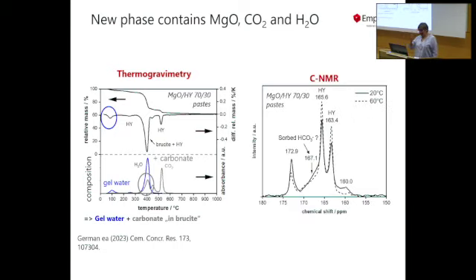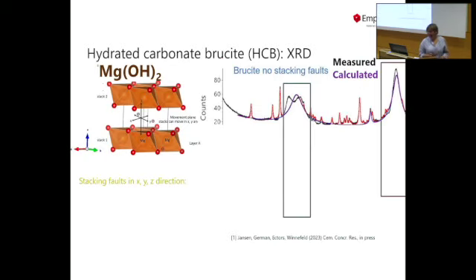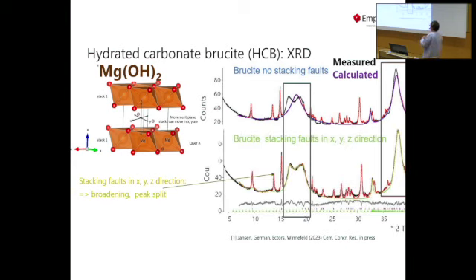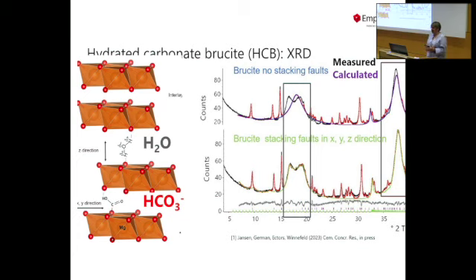So we also tried to figure out where the carbon is, and we did some solid state 13C NMR, and there we basically found two unknown peaks, which just told us we have somewhere a carbon in our structure. To make a long story short, we then went one step back and thought maybe it's a disordered brucite, and we used XRD to mirror what would happen if we allowed the brucite, which has layers like that, to move in this direction and this direction and this direction. And if we do that, then we in fact could reproduce what we've seen before experimentally by XRD.